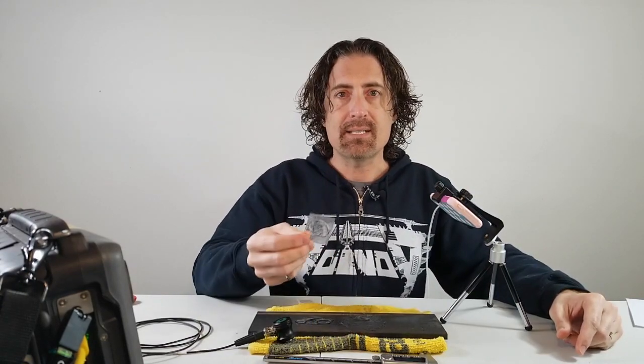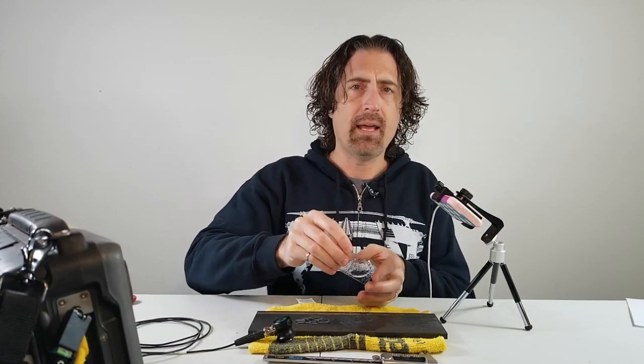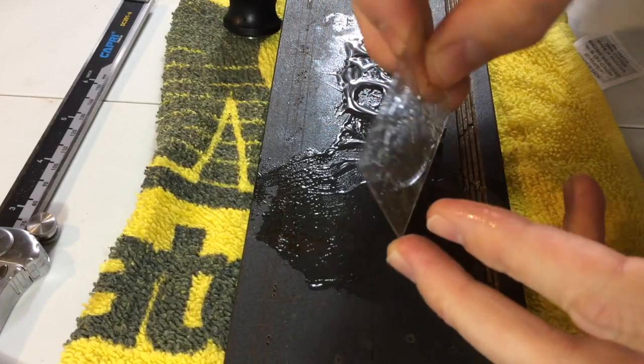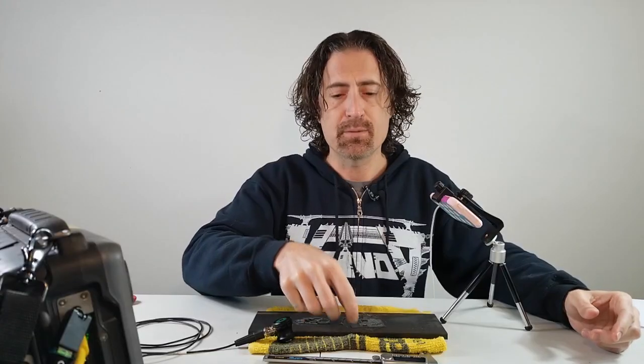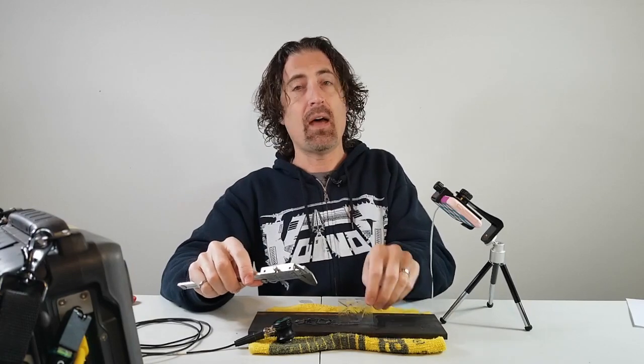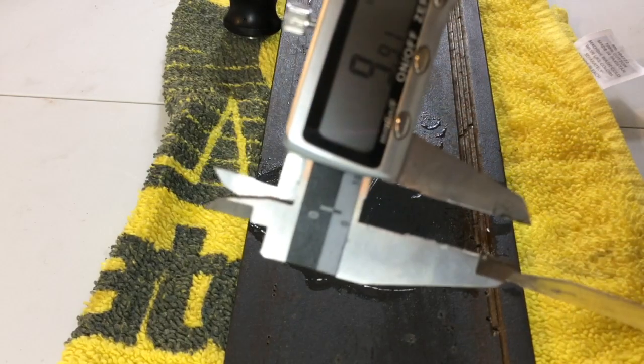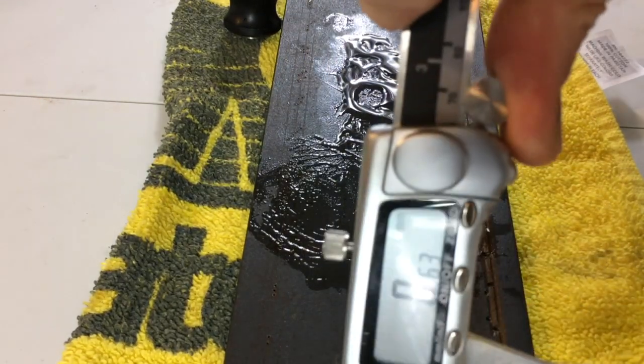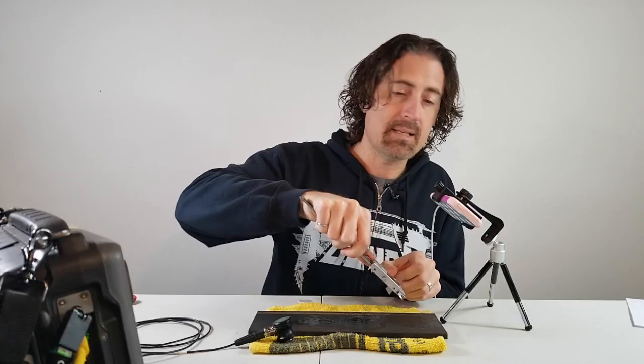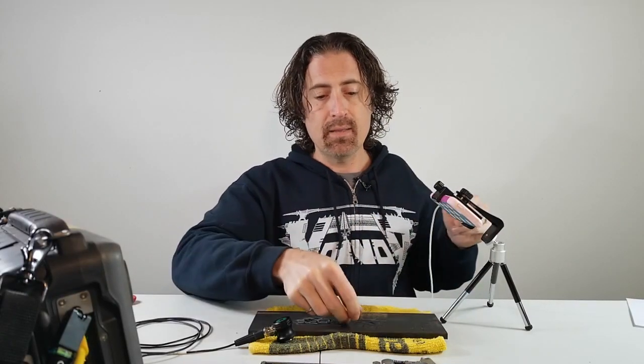So this little piece of plastic that I've got is probably polyethylene terephthalate, or PET. And the velocity of sound through this is about 1900 meters per second, which is about a third what it is through steel. So if I had a difference of 1.5 millimeters, then if I divide that by 3, I should get about the thickness of this thing. That's about 0.5. And we'll measure this, and we get about 0.6, not bad. So it's kind of neat. Using the echo-to-echo technique, not only are we able to take the coating thickness out, we're actually able to measure the coating thickness.